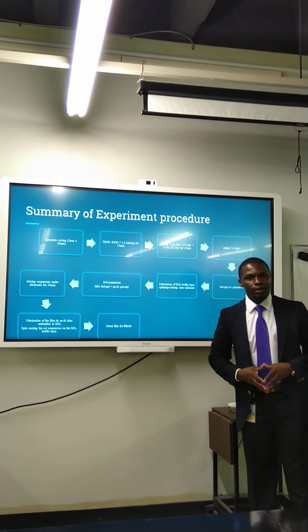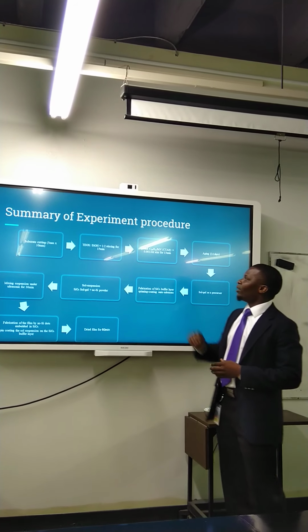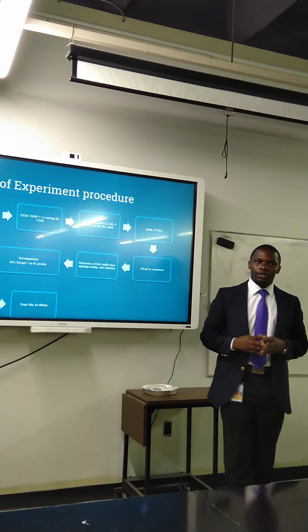In substrate cutting measurements, I used the 5mm by 10mm substrate size, and then from there I made the TEOS solution, and then the CTAB and the sol-gel solution. After that, we left the sol-gel and the TEOS solution for 14 days.